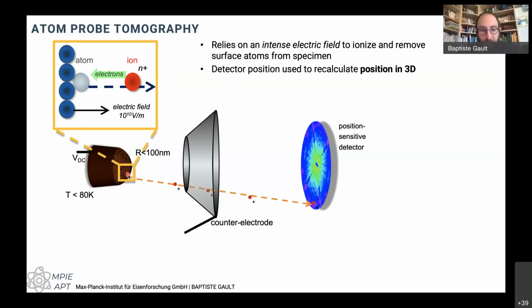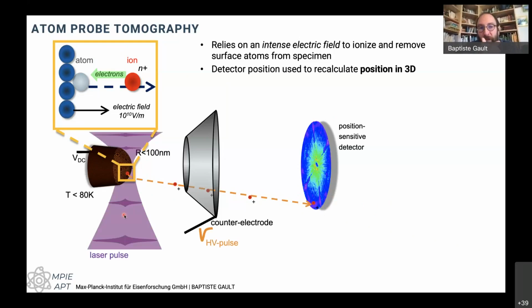The second aspect is that we want to be able to time the moments when these ions are created. So there's two ways to do this. Either we want to increase temporarily the field, because the probability that the atom is going to become an ion and field evaporate is proportional to the intensity of the field. So I can just, on top of the DC voltage, apply high voltage pulses directly on the counter electrode, so they would be negative. It's going to repel the electrons a little bit more, and that's going to increase the positive field at the apex of the needle temporarily for a couple of nanoseconds.